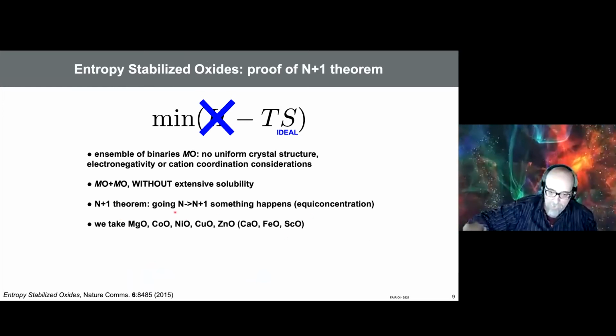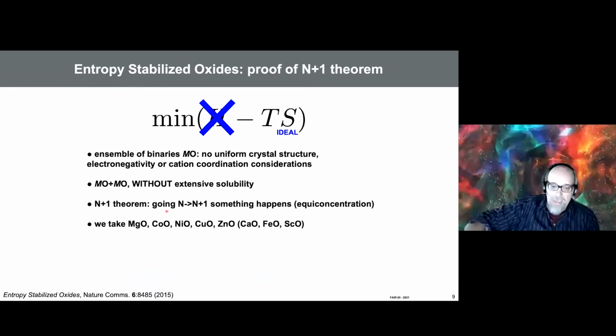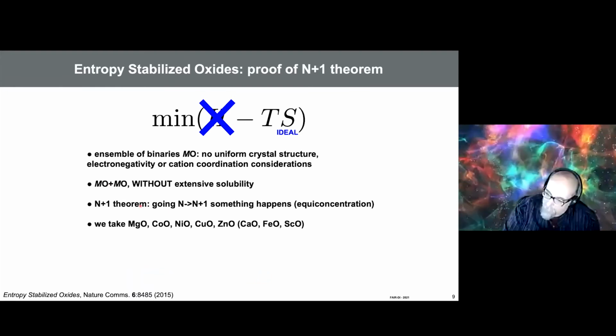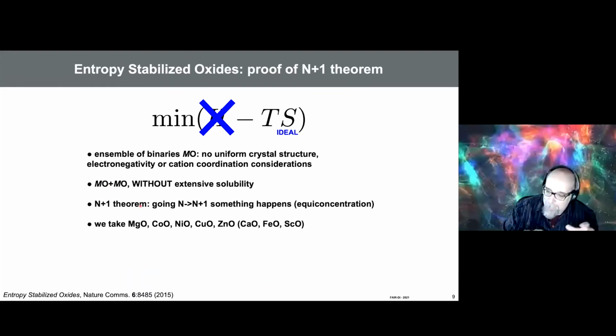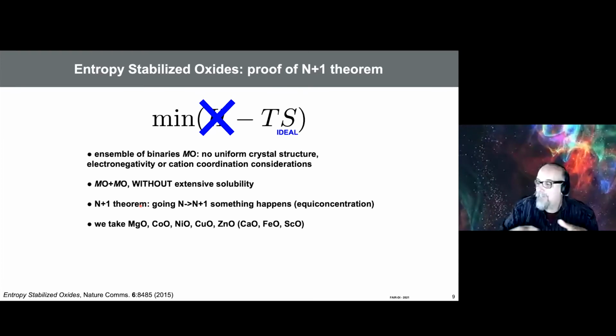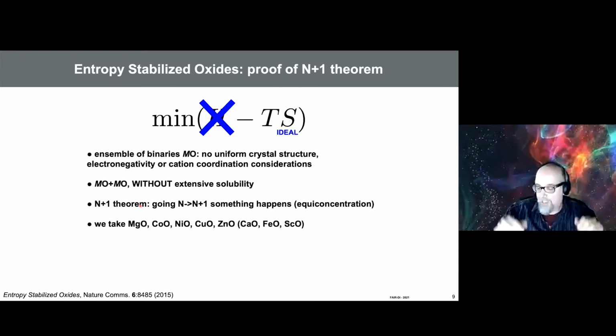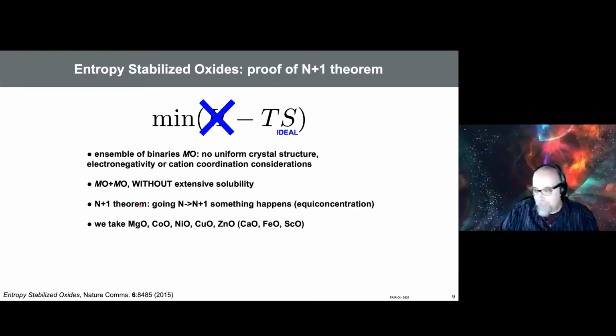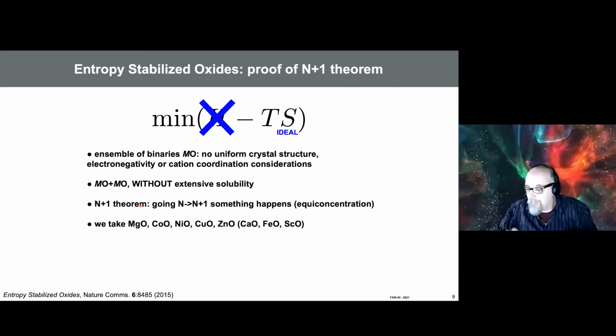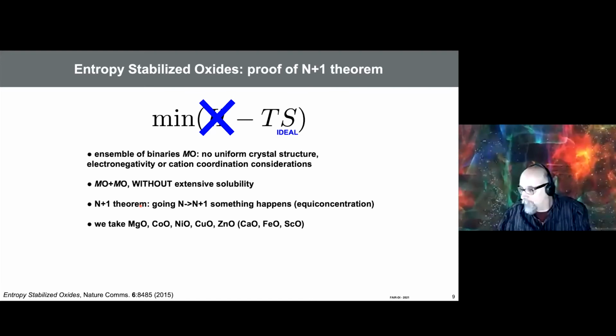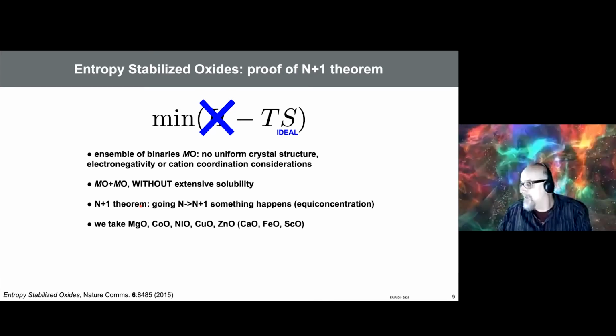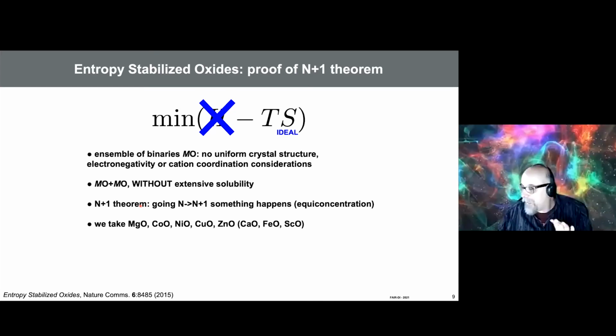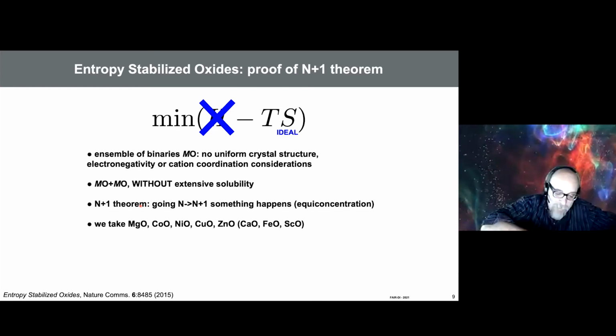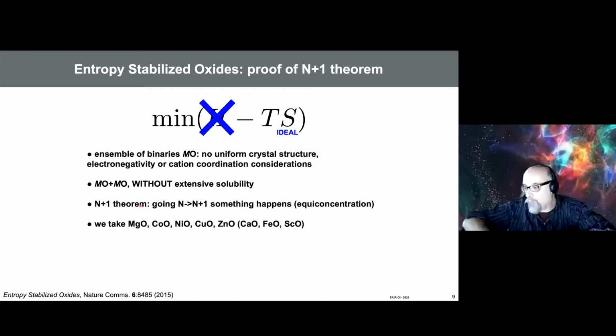Those are all powders. And then we take n of them, we mix them, we cook them, and then we see what happens at high temperature, if there is this order-disorder transition with n. And then, if nothing happens, we do it with n plus 1, okay? And we repeat the process. That's actually very simple. Does it happen with n or not? Does it happen with n plus 1 or not?